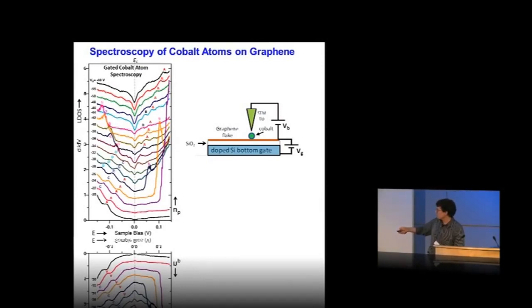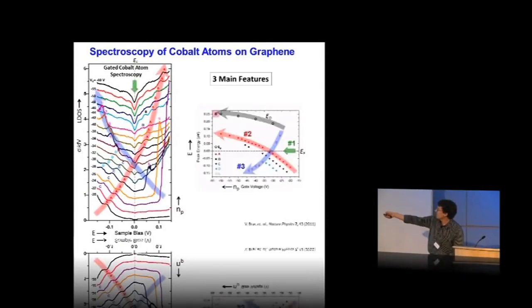It looks kind of complicated, but it's not so bad. There are really three main features. The first, at the center, is this dip at the Fermi level, which is gate independent. We believe that dip is simply an inelastic feature due to the vibrations of the cobalt atom. I don't want to focus on that in this talk, unless you force me to. What I'd rather focus on are these other features, which change with the gate voltage.